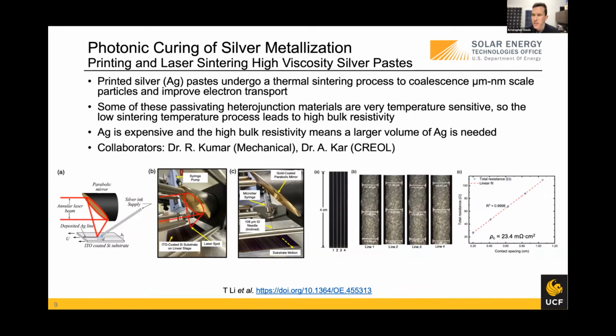And another project that I've been working on that we actually just wrapped up with Dr. Kumar and Dr. Kar in mechanical and CREOL respectively, is looking at photonic curing of silver metallization. So in this case, with a lot of these heterostructures, they're very temperature sensitive. So when you go to print the silver metal lines, you have to do a thermal sintering step to allow the particles to coalesce, so you get good transport. But you can't heat the wafers up above, say, 200 degrees C, or you start to cause some issues. You start to get defects form and stuff like that.